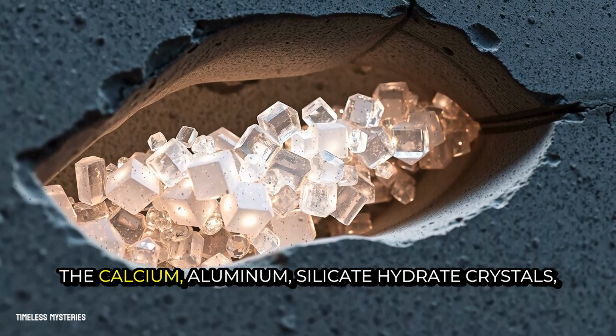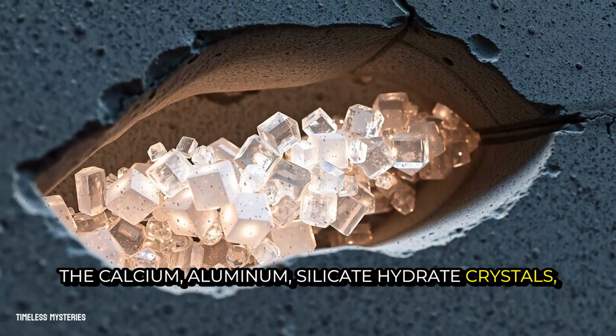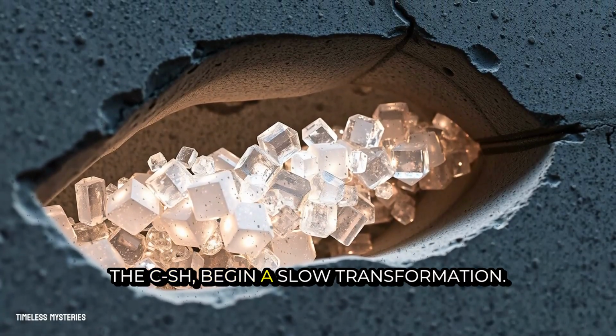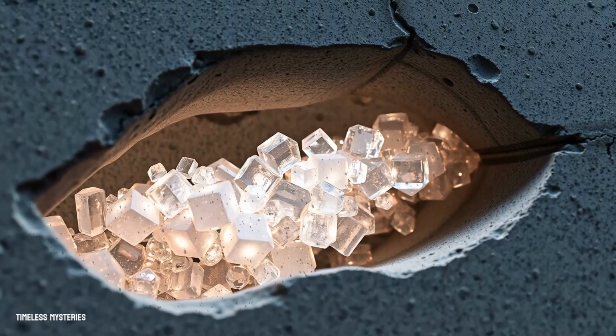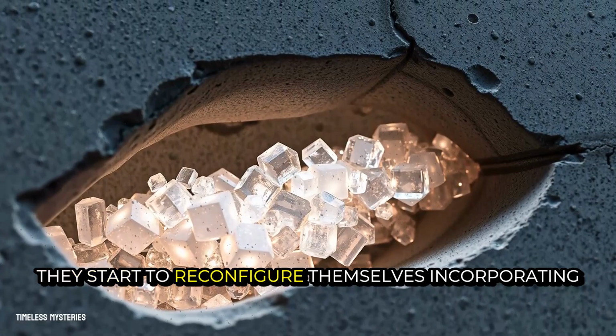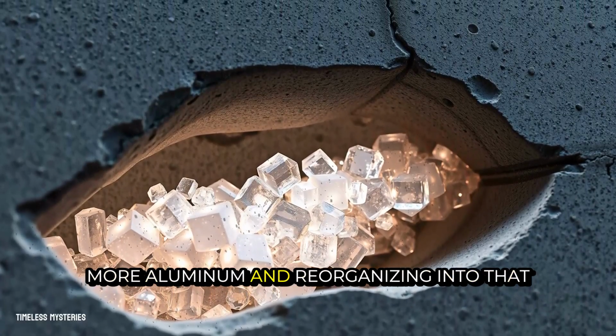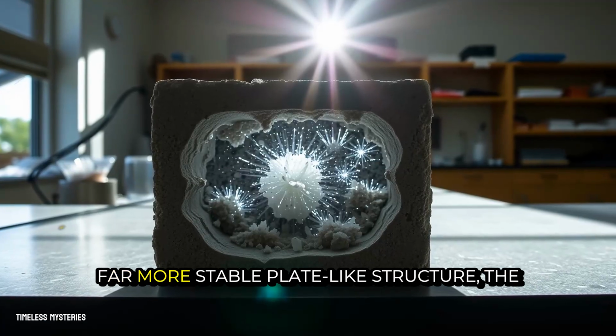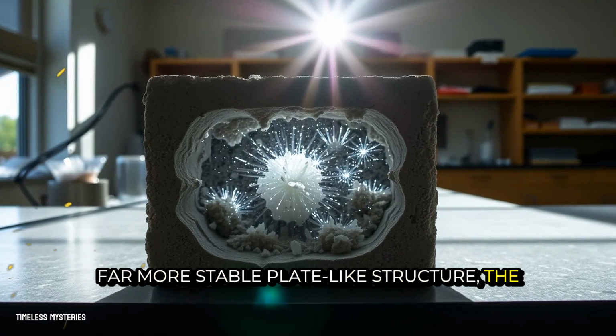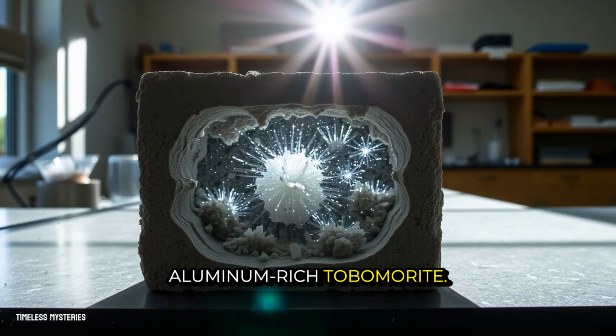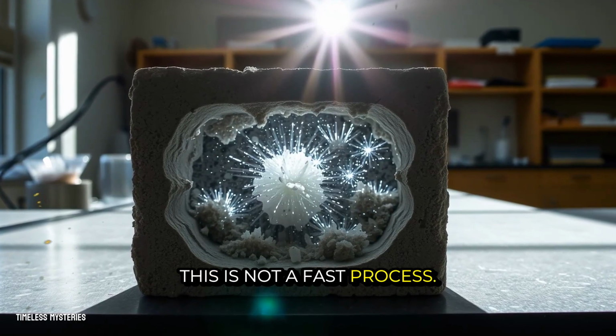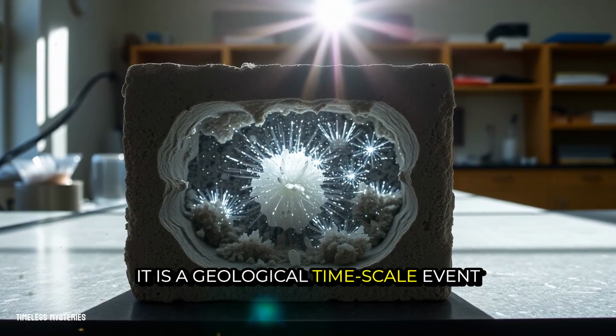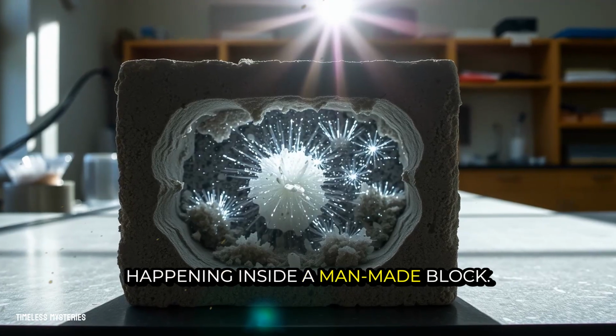The calcium-aluminum silicate hydrate crystals, the CASH, begin a slow transformation. They start to reconfigure themselves, incorporating more aluminum and reorganizing into that far more stable, plate-like structure, the aluminum-rich Tobermorite. This is not a fast process. It is a geological timescale event happening inside a man-made block.